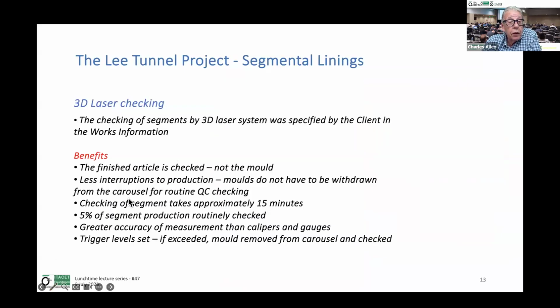The benefit of this is the finished article is checked and not the mould. There are less interruptions in production because you don't have to withdraw the mould from the carousel for routine checking. Checking of a segment takes approximately 15 minutes, and we checked 5% of production routinely, and it gave a much greater accuracy of measurement than calipers and gauges, which is important when you're using a universal ring, which doesn't have a baseline edge that you can measure from.